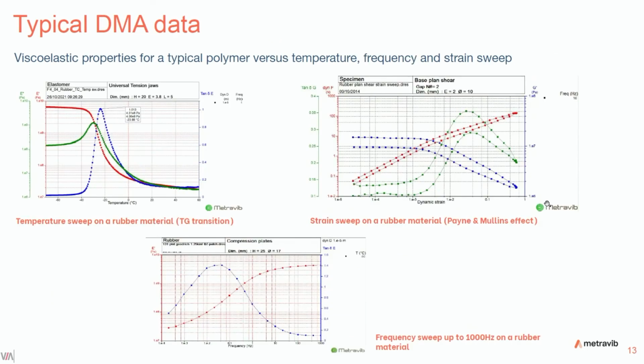Typical DMA data, a classical DMA test. First of all, maybe a temperature sweep in order to characterize some transitions, alpha transition or beta transition. As you can see on the picture, the evolution of E prime as a function of the temperature, the tangent delta, and the evolution of E double prime in the same characterization.